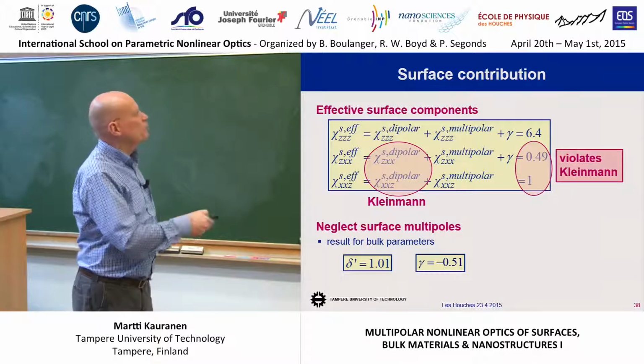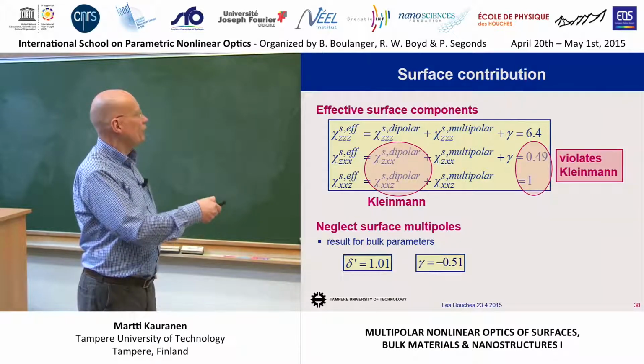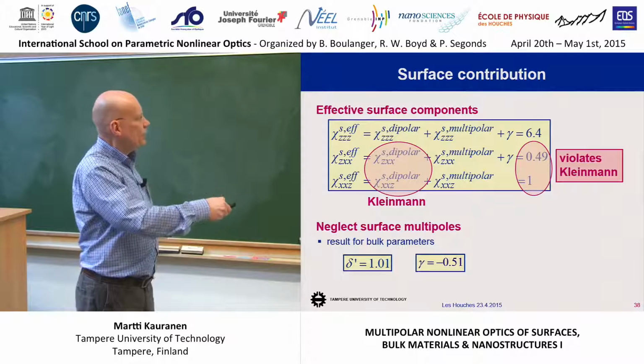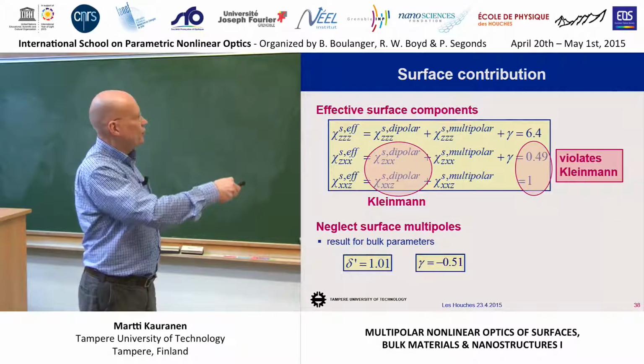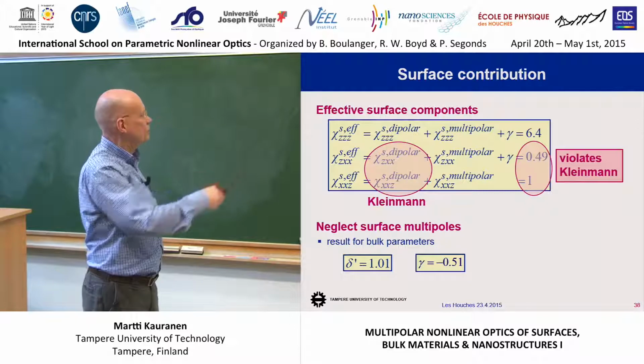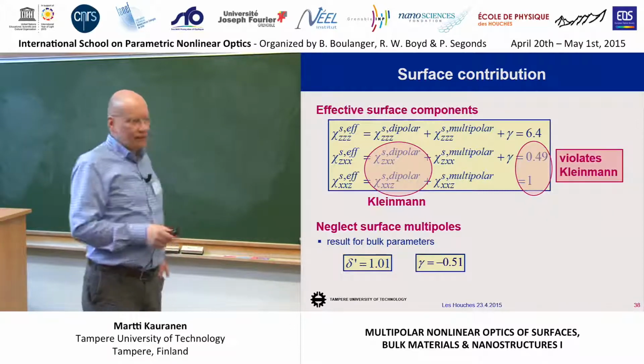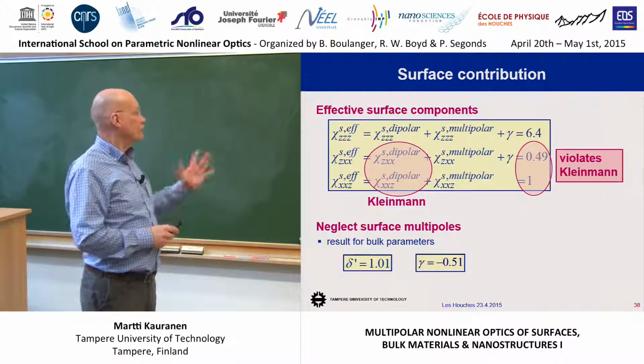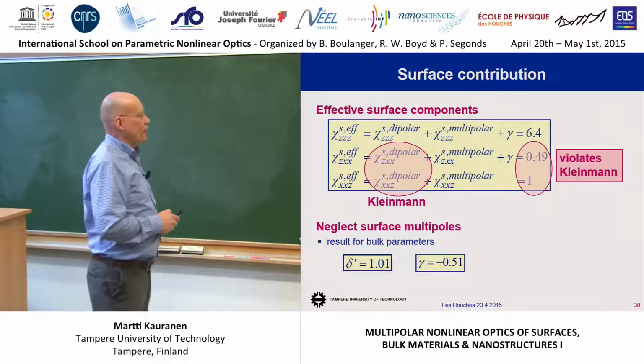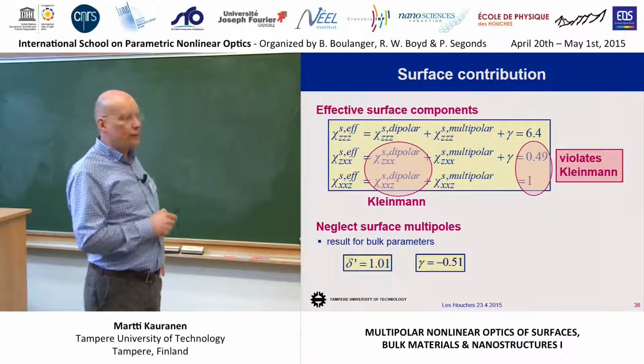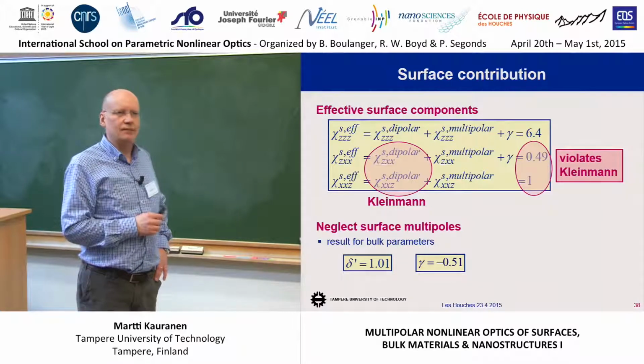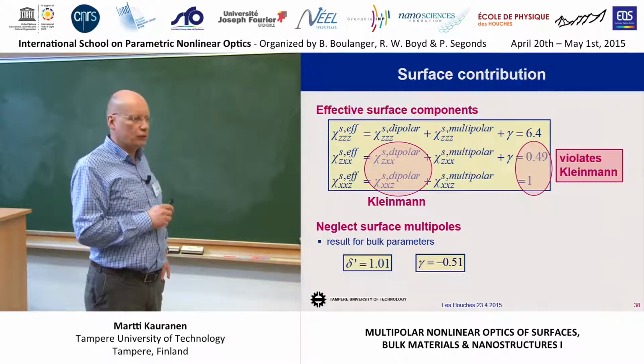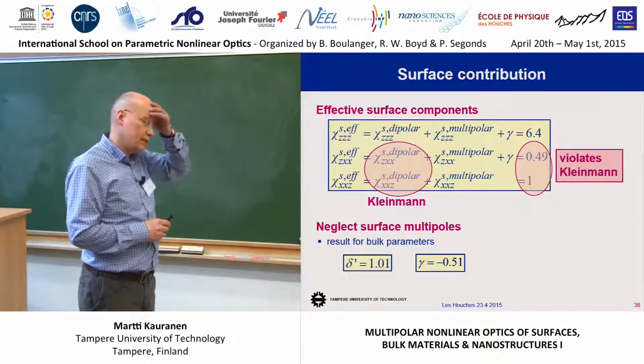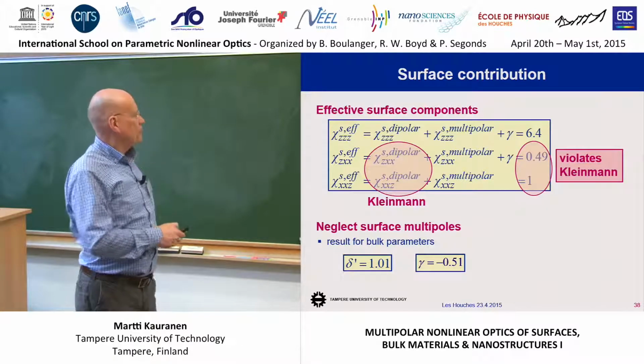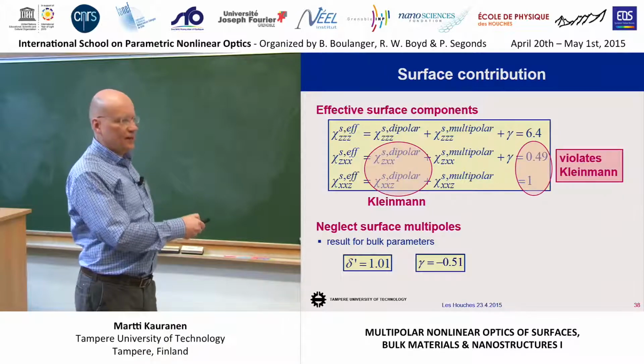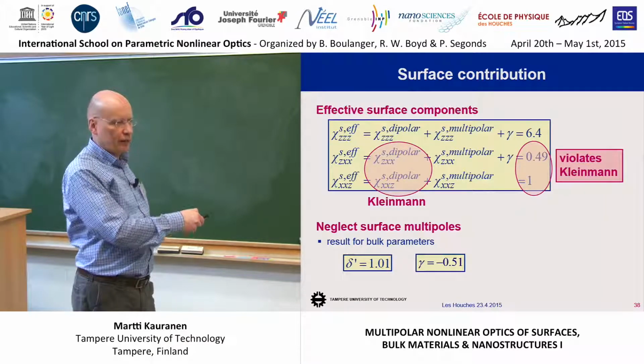So whether there's some surface multipole contribution, it can be absorbed here. In some sense, I'm crossing out this part here. These contributions are hidden here. Now, a glass, BK7 glass, is highly transparent, so you would expect that Kleinman symmetry is at least valid to some extent. I did not mention Kleinman symmetry in the first lecture, but Kleinman symmetry means that you can change the order of these indices any way you like, and you get the same number.